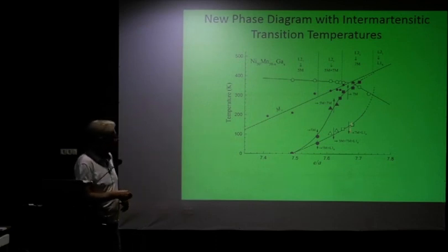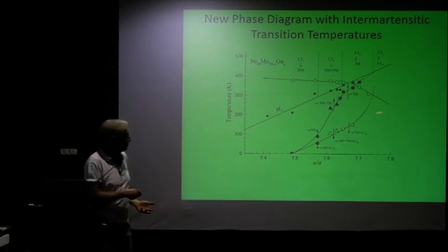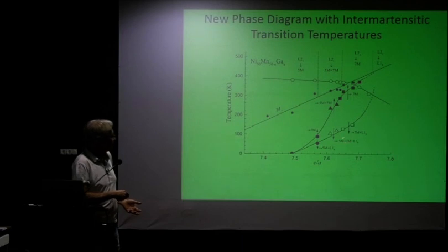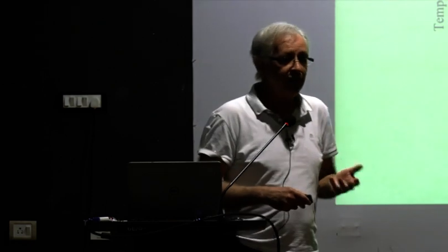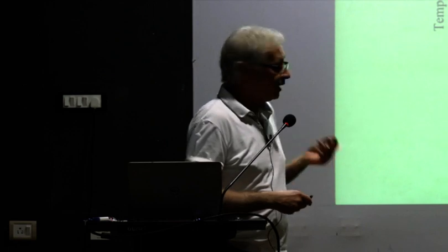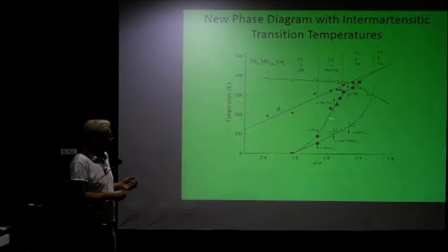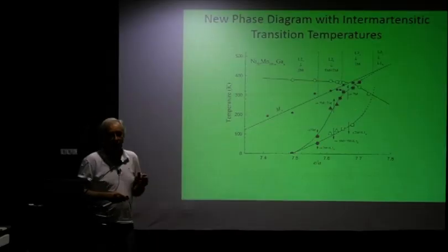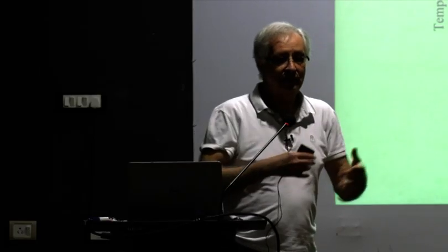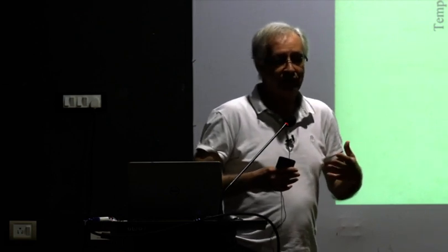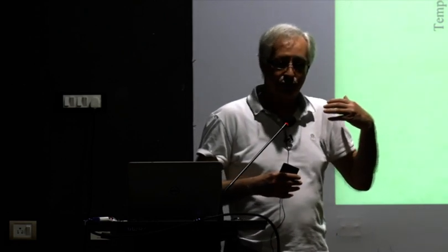Yeah? And it seems that the ground state is L10 anyhow, because the L10 state appears below certain temperatures, be it a mixture. So in all these Häuslers, the actual true ground state is the L10 state, meaning that these modulated states that appear between the L21 and the L10 have to be some kinds of adaptive phases, frustrated phases, so that it's like supercooling.